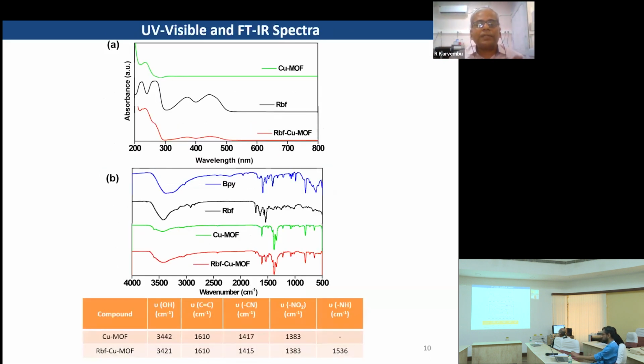Then we characterized the materials by means of UV-visible and FTIR spectroscopic techniques. If you look at the riboflavin-modified copper MOF, there are some absorption bands between 300 and 500 nm, which are characteristic of riboflavin, indicating that riboflavin is incorporated into the copper MOF. In the IR spectra, we found the NH asymmetric bending vibration in the riboflavin-modified copper MOF, due to the presence of riboflavin.